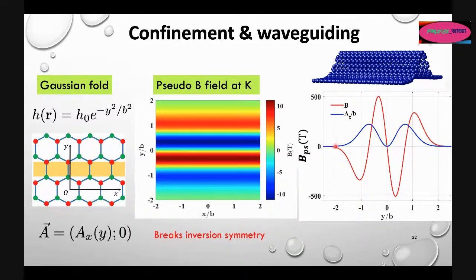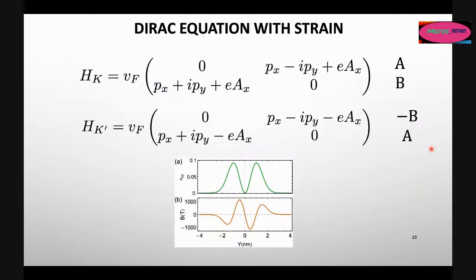Now, the fact that the pseudo gauge field has a double barrier structure makes it easier. This is a picture of how the pseudo field changes in position, and you see that it alternates colors. So the fact that the gauge field has a double barrier structure makes it easier to work with Hamiltonians in the continuum limit, as I mentioned before, because I have an explicit form for the Gaussian and the gauge field, and I can attempt a solution not only numerically but also analytically.